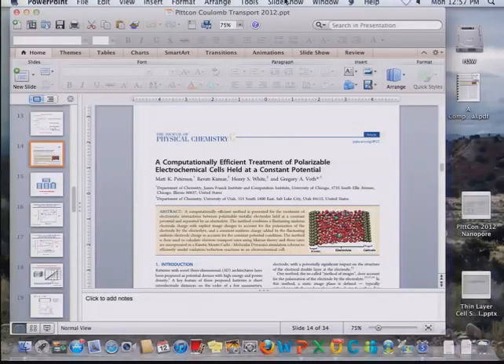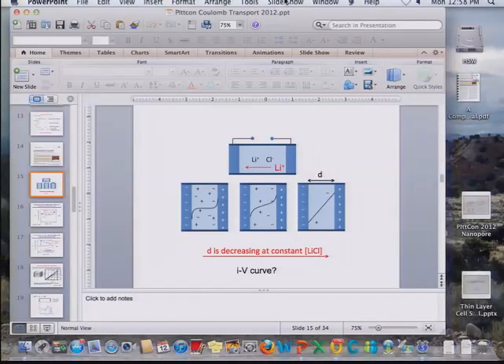But these are kinetic Monte Carlo molecular dynamics simulations of exactly the same problem that I just described to you, where you have solvent, a few ions, you start pushing the electrodes together, and you calculate the current flow resulting from the molecule diffusing back and forth, shuttling between the electrodes. And when you do that, you clearly see enhancements in the transport and variations in the electron transfer rate resulting from the overlap of the two electrical double layers. So that's another approach. But we're doing more continuum-based calculations and experiments. I actually believe the experiments more than the calculations for once.